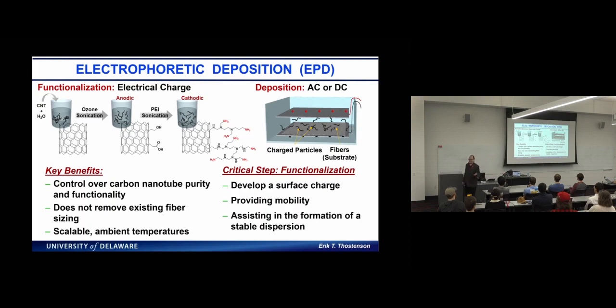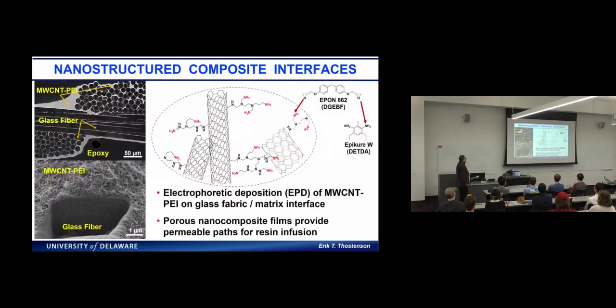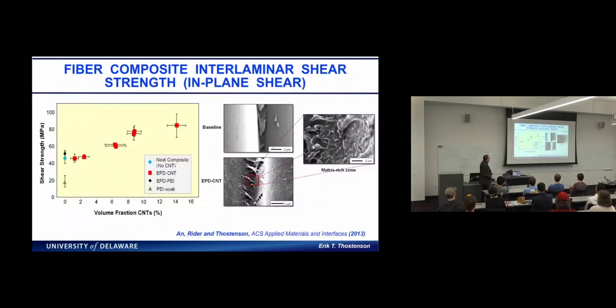So instead of just carbon and glass fibers, we can now deposit on a wide range of natural and synthetic fibers and organic fibers. And that's really been the enabling technology. What's interesting with this process is that we back it with an electrode. This is the chemistry that we're using. We chose this for composite materials, but it's been an interesting process. So we can modify the shear strength, or basically the bond strength between the layers, and also the interface.